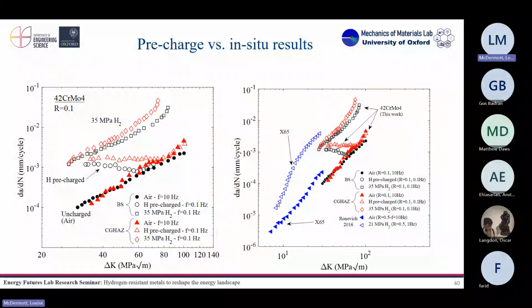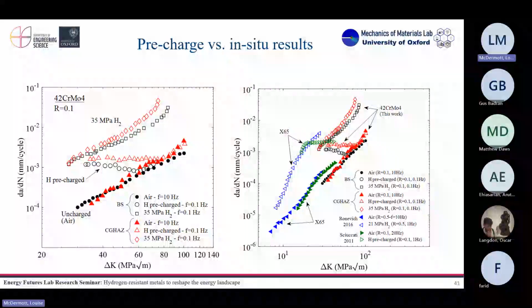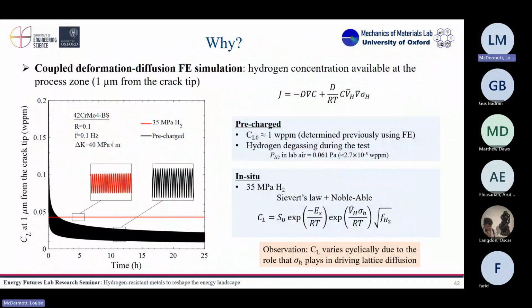Even though we couldn't find a paper where they compared both methods, we compared two research papers where the same material was tested with the two different approaches. So this is for a hydrogen atmosphere, in this case at 21 megapascals, and then some other people in the same material but with pre-charged samples, with samples that were tested in air after hydrogen charging. And they also observed the same exact behavior as we did, okay? But they didn't notice these differences because they were at different rates, okay? So we said, why is this happening?